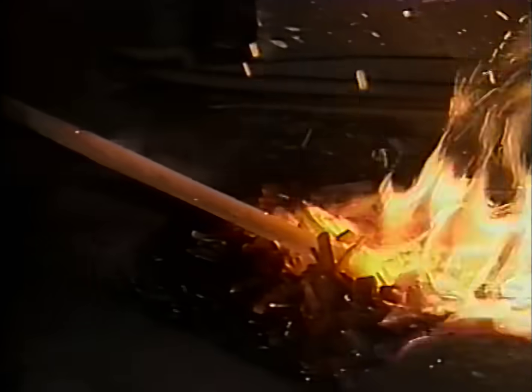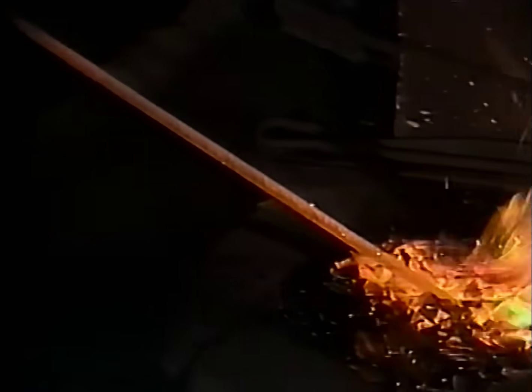Because he must be able to distinguish very subtle changes in the color of the hot sword, Yoshindo performs yakiide in pitch blackness. Carefully passing the sword through the forge with one hand, he pumps air into the forge. Each push of the piston changes the forge temperature, and this has to be judged by the color of the sword. Maintaining the temperature between 725 and 780 degrees Celsius, Yoshindo ensures that the sword is heated evenly all round.